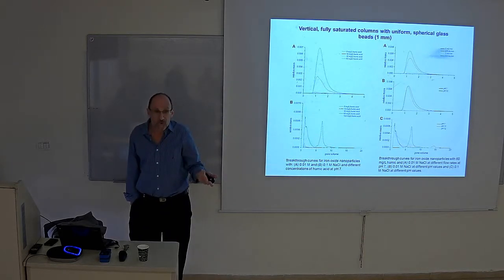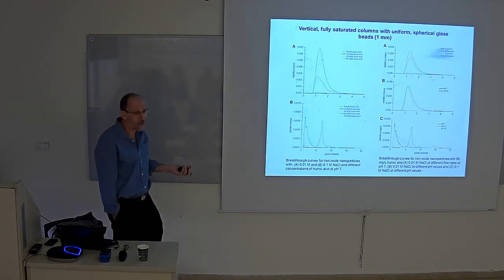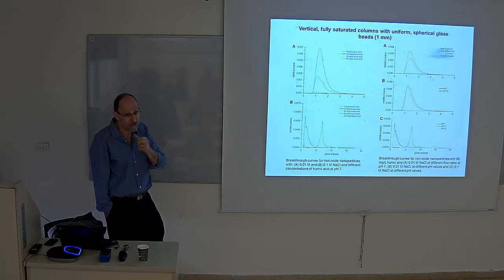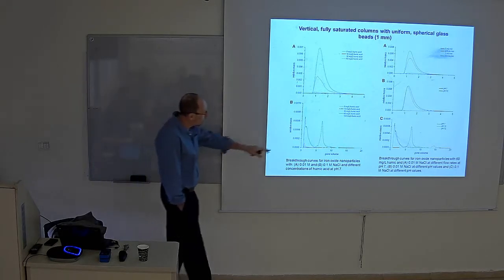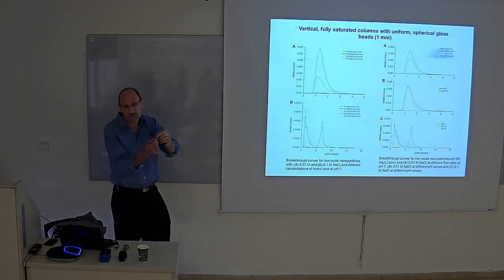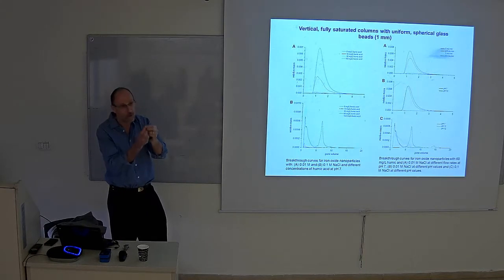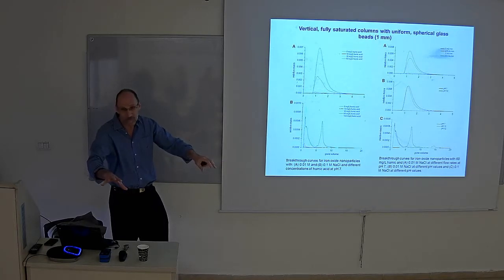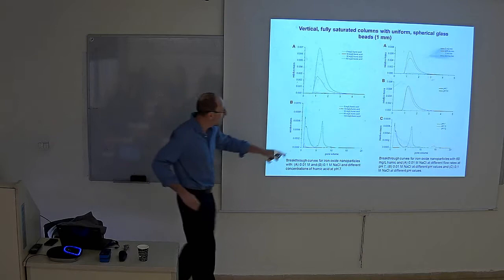Say, how the hell am I supposed to model that? In fact, what's actually going on? The colloids don't do that as much. Okay? So what's happening with the nanoparticles is as they're moving through the system, they're aggregating, blocking the pores, so you get a change in the flow rate, and they block, and then the pressure builds up, and then they break through. Okay, so I can wave my hands and say that must be what's happening.